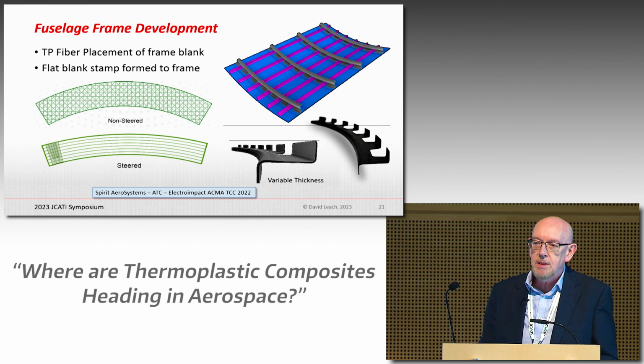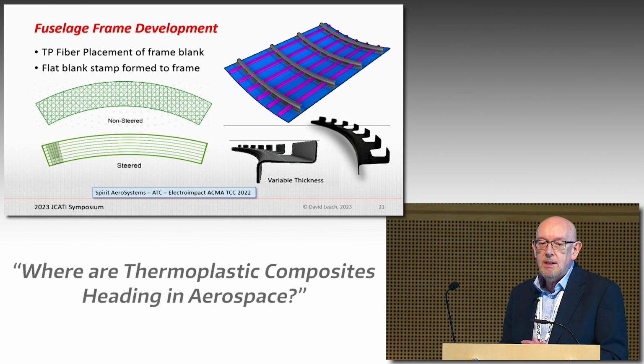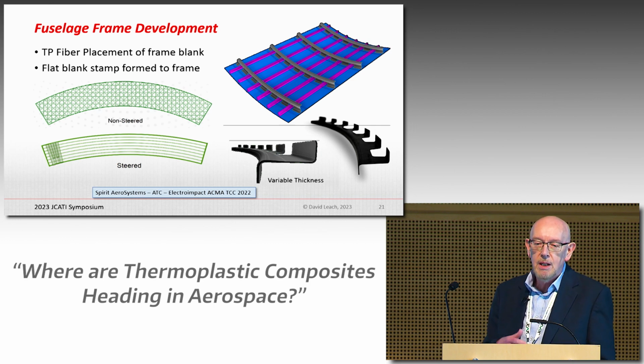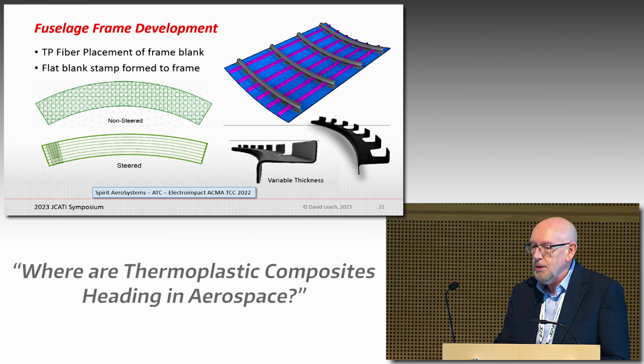Again, something that's been established in thermoset materials for some time, but in the thermoplastics with the very rigid body input material and the very viscous polymers, that's not something that's very straightforward to do. But Electro-Impact came up with the process to be able to steer, as an example, the 0-degree plies around the radius, and the 90s and the 45s, so they were radial.